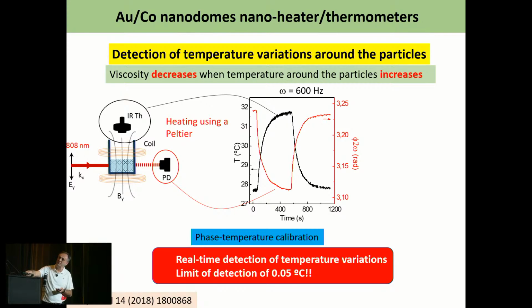Now we have the infrared thermometer, but now using a Peltier system, we controllably change the temperature of the system. And now we measure the phase lag in the system. And you see here, in black is the temperature measured by the infrared thermometer, and in red is the phase change because of the viscosity. And you can see there is a one-to-one correlation. So we can use this phase change to actually measure the temperature of the liquid. And using this approach, we can have a detection limit of about 0.05 degrees.